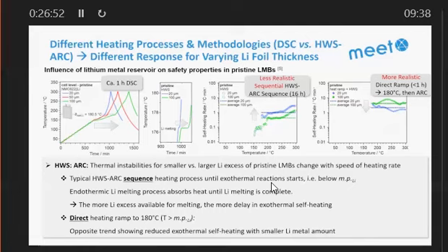If we then really ramp it up without waiting, we simply ramp it up until 180 degrees C, and then we do the safety test, we see that the 20 micron lithium is reacting less than 100 micron lithium. So we always get different responses for different results. What is a realistic safety test? A realistic safety test is something which is close to what happens in a car. In a car, when you have a safety incident, does your cell heat up within 16 hours? No. But this is how all ARC data is produced in literature. Okay, so the thing is, safety is something which really depends on how you measure it.